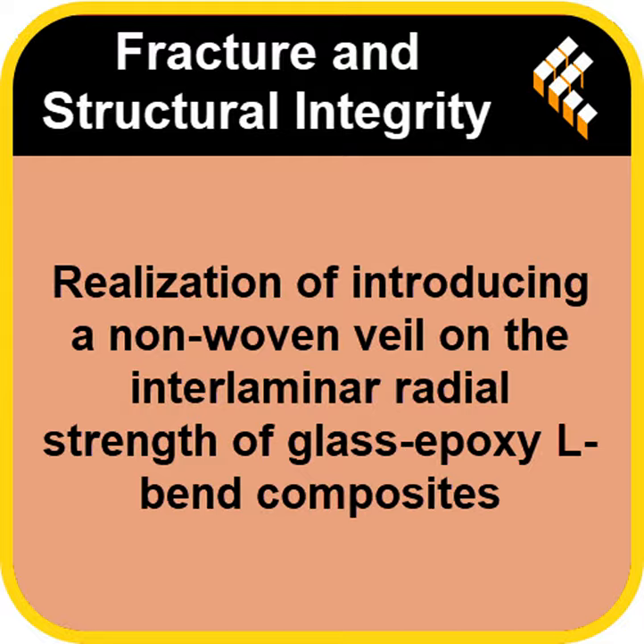Brittle failure. And the stats back this up. Clearly, the improvements in ILRS for the 15 and 20 g/m² carbon samples were statistically highly significant, really tiny p-values, less than 0.001. But the 30 g/m² sample showed a statistically significant reduction in ILRS. The numbers confirm it was actively detrimental. Wow. So less is definitely more when it comes to high-stiffness carbon veils. Okay, what about the glass veils then? They're less stiff. Do they show the same pattern?